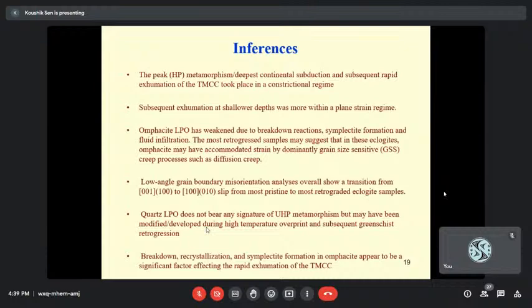And finally, the breakdown, recrystallization, and symplectite formation in omphacite appear to be a significant factor affecting the rapid exhumation of the TMCC. So what we plan to do, I hope I'll be able to do it in the near future, is target the symplectites for EBSD analysis and index both amphibole and pyroxene, to see whether they are epitaxial or topotaxial, and what the relationship between them is during the breakdown, and whether this can give us any insight into the strain regime, and also the strain regime vis-a-vis a particular pressure-temperature condition. This is future work that I have in mind, and hopefully I'll be able to pull it off in the near future.